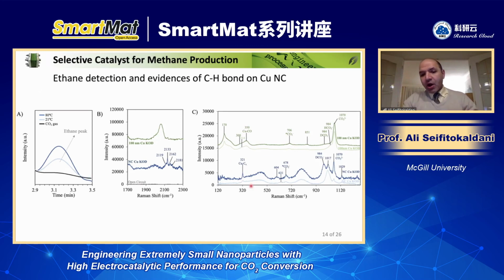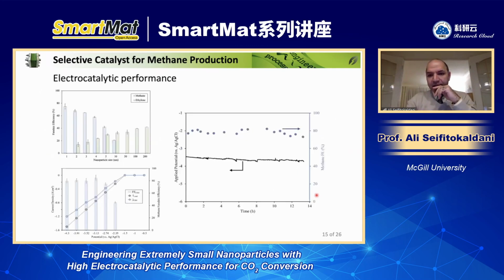And then also our Raman spectroscopy, in situ Raman, showed that on small particles you have some features demonstrating that there is a CC bond, but on large particles we didn't see that, simply because on large particles, as soon as the ethylene is generated, it leaves the surface. So you don't have really a high population of ethylene adsorbed on the surface. But on small particles, you see those features showing that the CC and also the CH bond are present there.